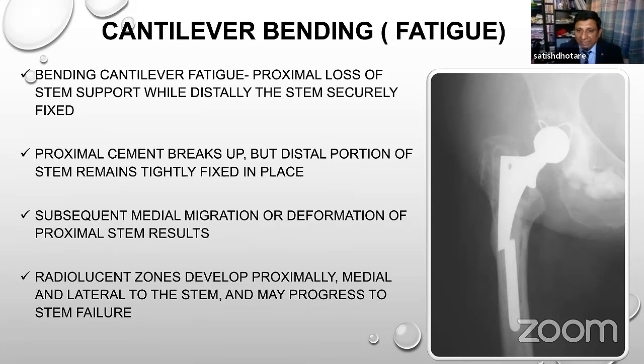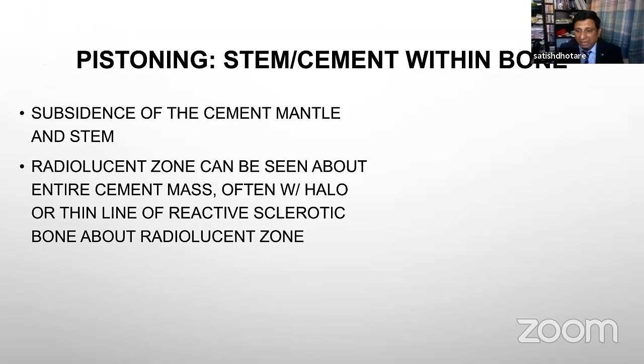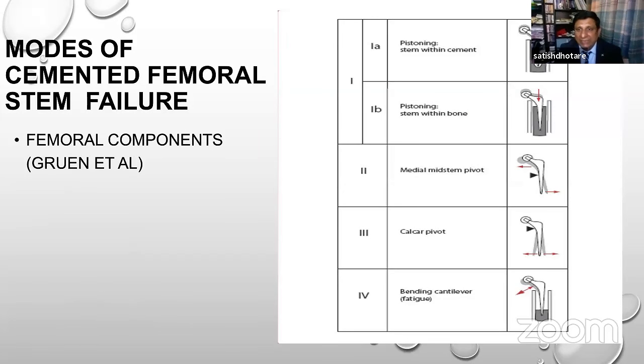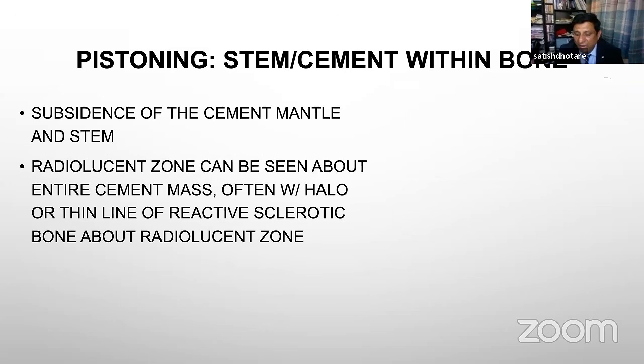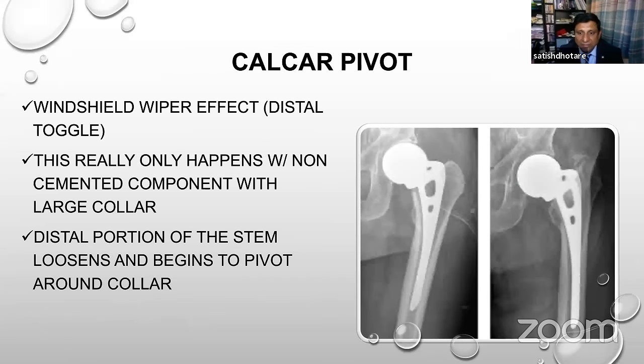I think these are the most commonly seen modes, and what I have seen most is cantilever bend and type 1 pistoning, which is mainly the stem with the cement. So these are the most common ways. Calcar pivot, again, is not very common these days, at least maybe in the olden days when cementing techniques were not right or prostheses were not right. Again, it also depends on the prosthesis type, because this is subsidence which you'll see with the polished taper, but not with the Elite stem, because those had a rough metal surface.